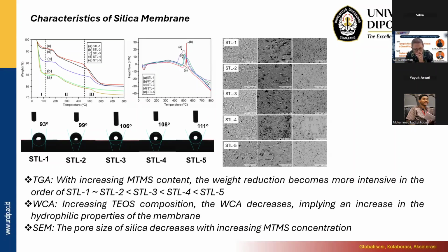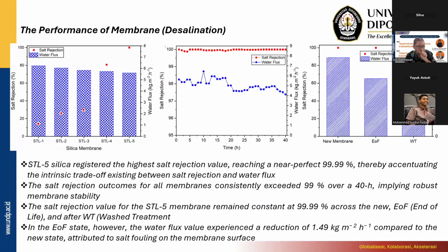After that, I tested the membrane in desalination. You can see here that by increasing the MTMS, the salt rejection increases sharply, close to 100%, and the water flux decreases only slightly.